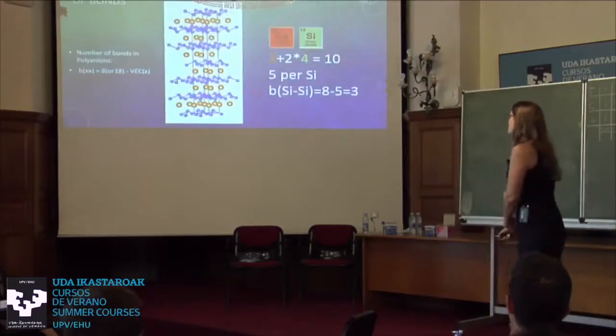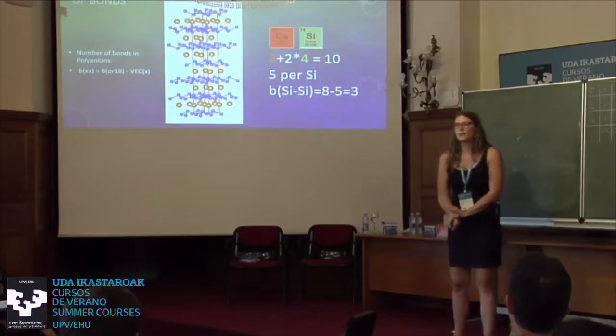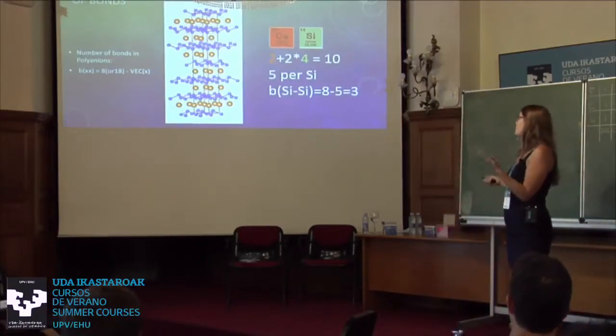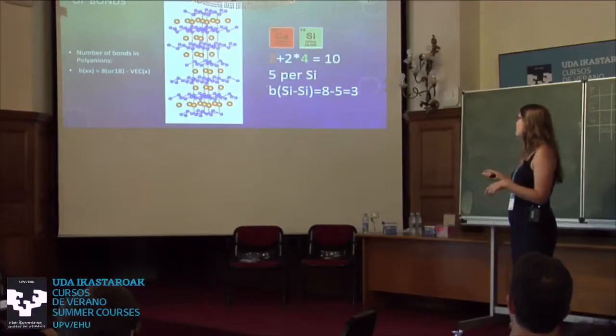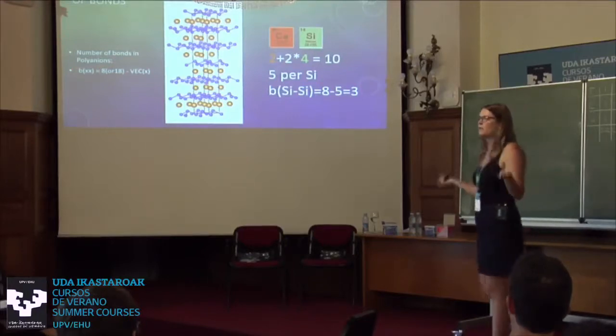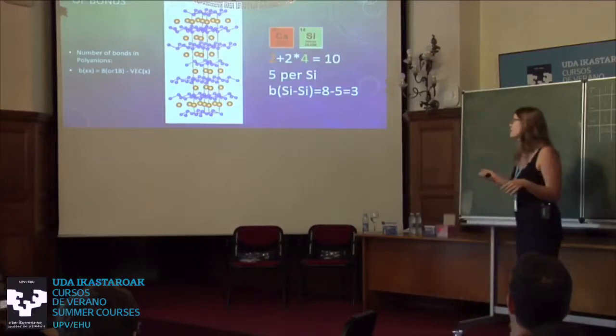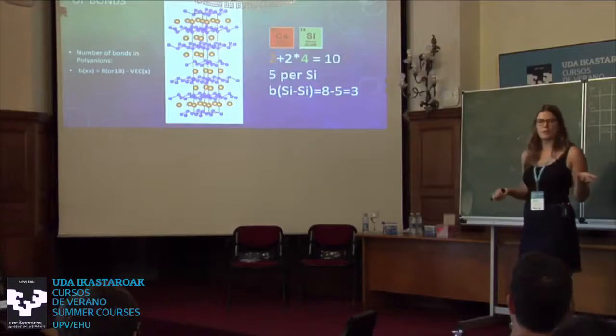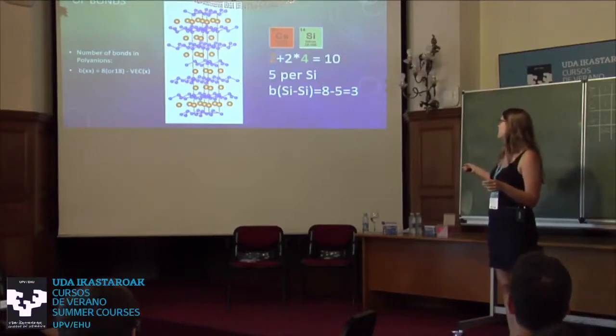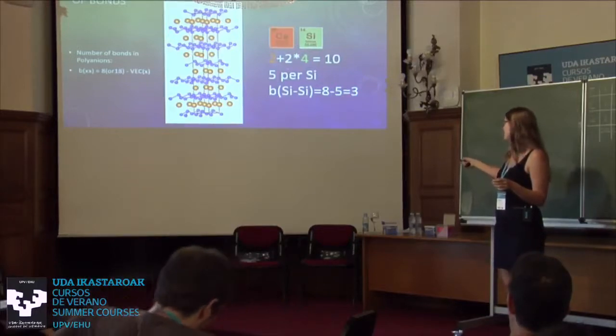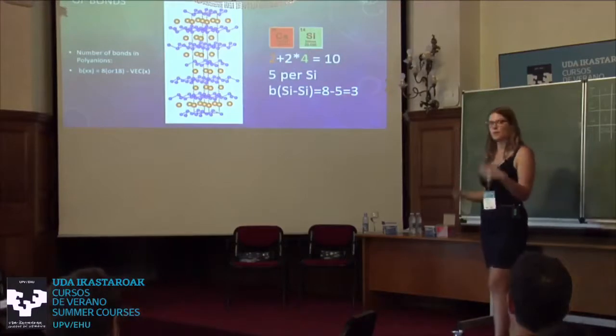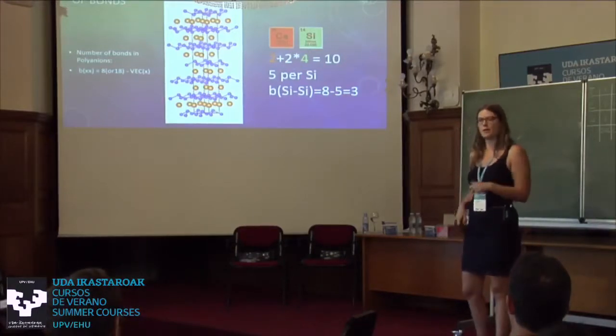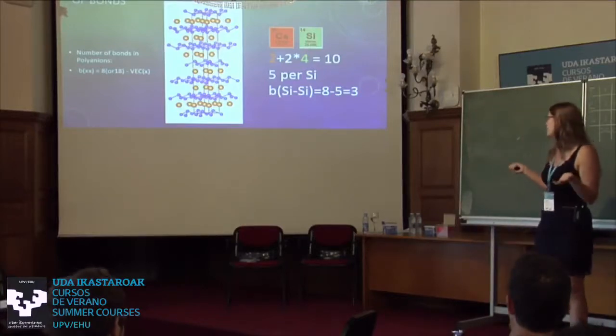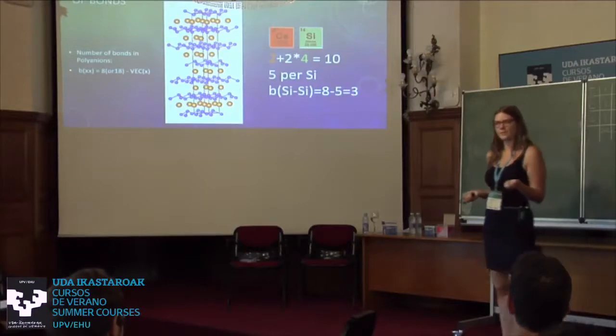And so if you know the crystal structure, there's a very easy thing to check if you still have a charge balanced compound. We already did it intuitively, but you can just follow this formula, which here is a bonding order. You just subtract the valence electron count you get, so here we had 5 per silicon, from 8 or 18. And then you get the bonding order. So this is the number of bonds you would expect to appear in the crystal structure. And you match it with the structure and see if you actually find this number of bonds there. So in the case of calcium silicide, you have 8 minus the 5 valence electron count we have, and you would get a bonding order of 3, and then you see it has 3 bonds, and then you know, okay, great, we have a charge balanced compound. However, if this doesn't match, and we would get 4 here, then you would have a metallic compound, okay?